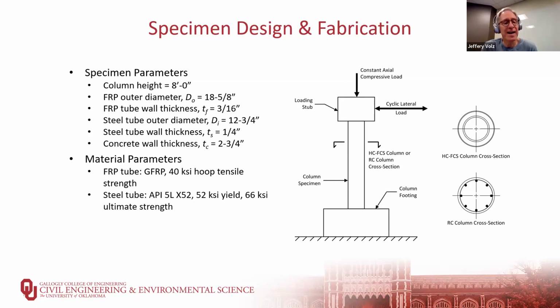The steel tube is an API 5L-X52, which has a yield strength of 52 KSI and an ultimate tensile strength of 66 KSI. That is very close to an ASTM A500 grade C steel. The API designation is very common in the oil and gas industry, which is what is readily available in the state of Oklahoma. But again, it's very close to an ASTM A500 grade C. The concrete core, this is where we're pushing this concept farther in our research project.